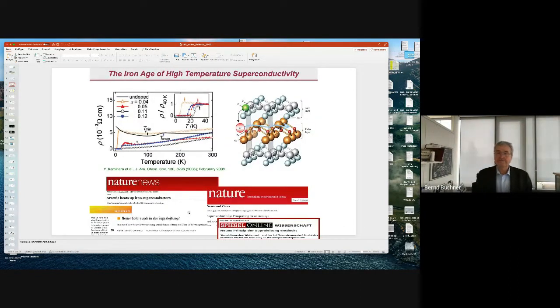So let's move to the beginning, and that's already 12 or 14 years ago when these iron-based superconductors were discovered in this paper by Kamihara and coworkers. They saw that this material, lanthanum oxygen iron arsenide, shows superconductivity at rather high temperatures, nearly 30 Kelvin, when doping the system with fluorine. And this attracted a lot of attention. It was like a rush similar to what happened in the cuprate case. There are just some newspapers shown here. And the reason was that after a short time, Tc rose to about 60 Kelvin.